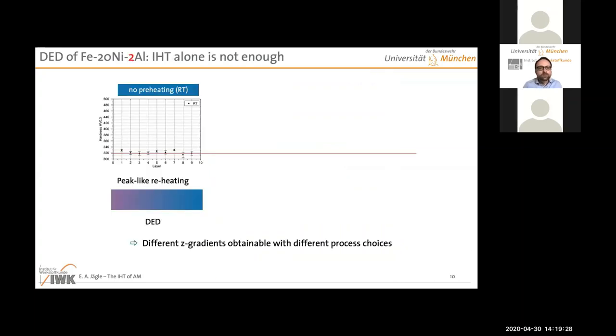All right. If we now take material that is a little bit lower in aluminium, iron 20 nickel 2 aluminium, there's not much happening. There's just not enough driving force for precipitation that the intrinsic heat treatment alone could do anything. However, this is very nice because it illustrates other kinds of heat input and how they can be effective.